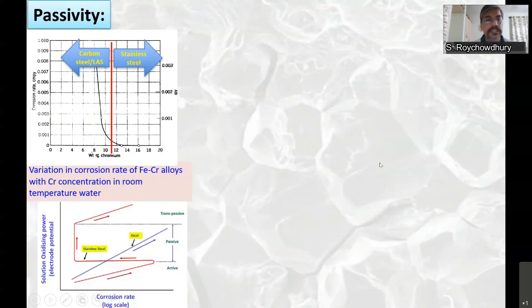So how do these two alloys compare, stainless steel versus carbon steel or low alloy steel? It is given schematically in this figure. The y-axis is the solution oxidizing power, the x-axis is the corrosion rate. For carbon steels or low alloy steels, the corrosion rate will keep on increasing with increase in this oxidizing potential. On the contrary, for the stainless steels there is a linear increase, but beyond a certain point there is a drastic reduction in corrosion rate, and this low corrosion rate is maintained for a wide range of oxidizing potentials. And of course, when the oxidizing potential becomes too high, the corrosion rate increases again. So this is the region where you have a very low corrosion rate, even though the material is anodic.